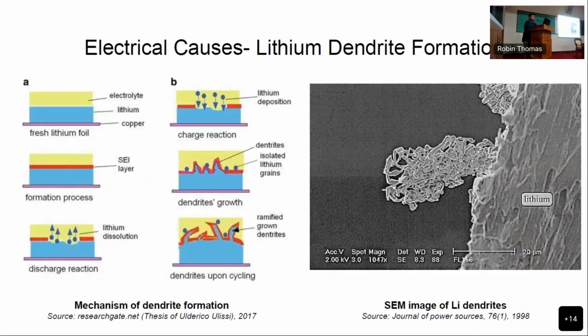So electrical causes. This is a quite interesting phenomenon that happens in lithium batteries. This is the phenomenon of dendrite formation. I'll explain it one by one. So here, this is a fresh lithium foil. This is an as-constructed battery, that is, a freshly constructed battery. In this, what happens is we have a gradual formation of the solid electrolyte interface. And here is where the discharge starts.